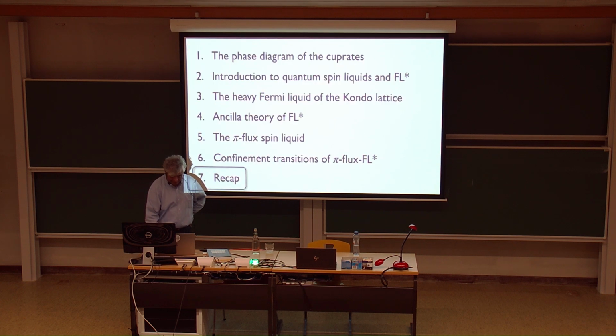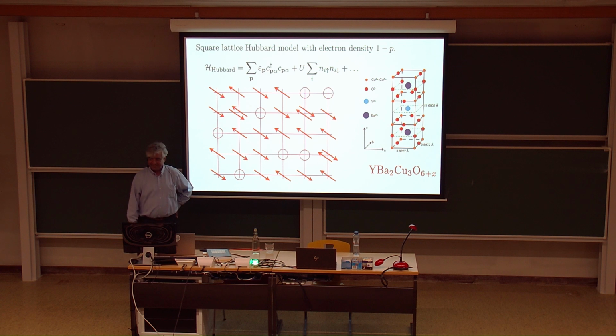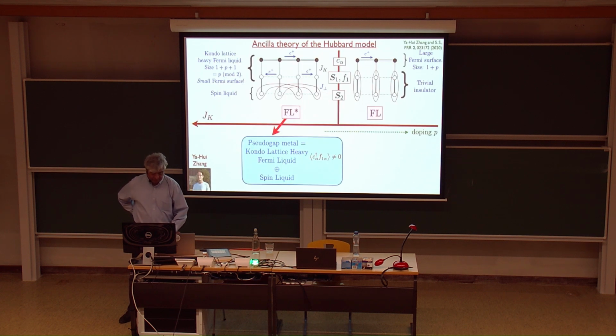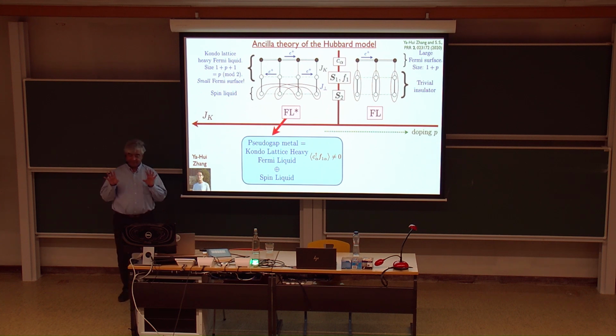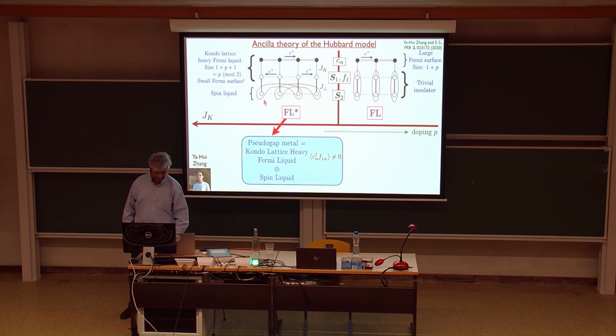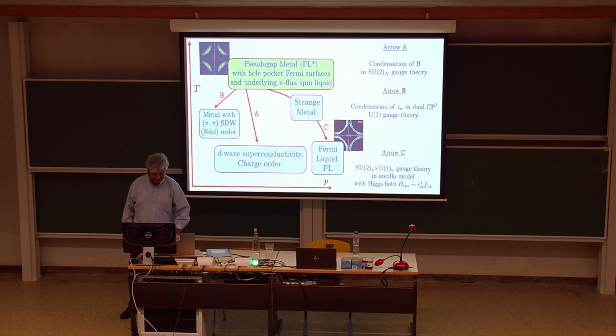All right. So to conclude, let me just recap. All this richness is in this very simple model, which even today is not that well understood, but it's probably responsible for high TC superconductivity. And underlying the physics of the cuprates, we propose is this kind of quantum phase transition. There are two different types of metals. There's the familiar metal, which is FL, and there's a novel metal, which we call FL star. And this FL star can be thought of as roughly the sum of a Kondo lattice heavy Fermi liquid and a spin liquid. And then when you confine the spin liquid through various methods, you get everything that's seen.